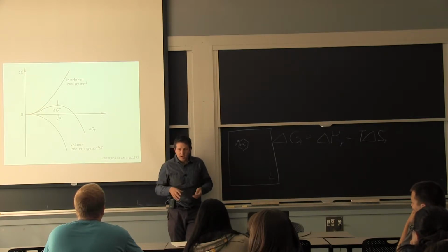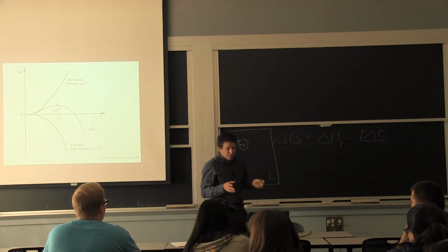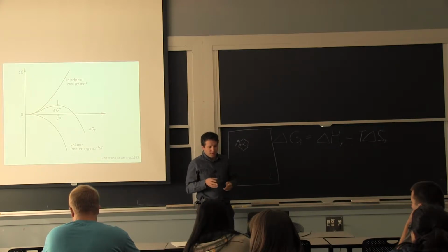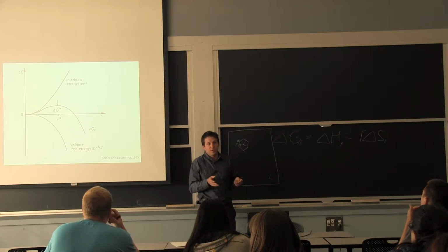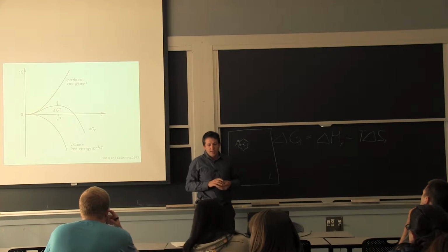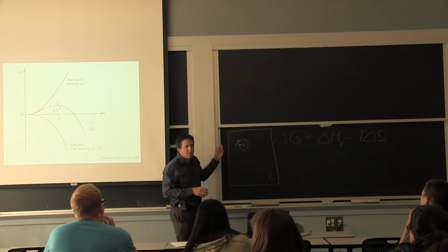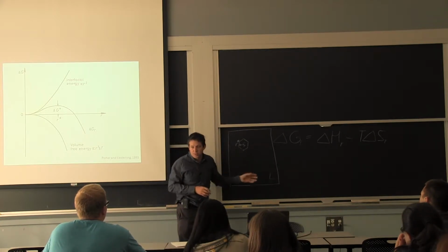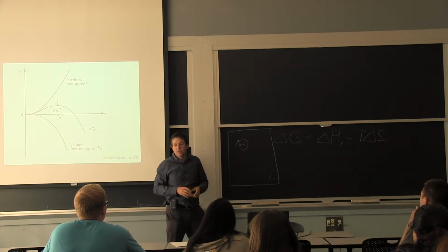So you want to try to avoid being in this situation, unless you want to, where all of a sudden the driving force is very high in terms of thermodynamics, but things can't move anymore. It's kind of tooling. And that's a way to, if you have very sophisticated chemistry, you can form amorphous metals by cooling them more quickly, because you get to a temperature that's low enough that they cannot organize and form this crystallized structure.